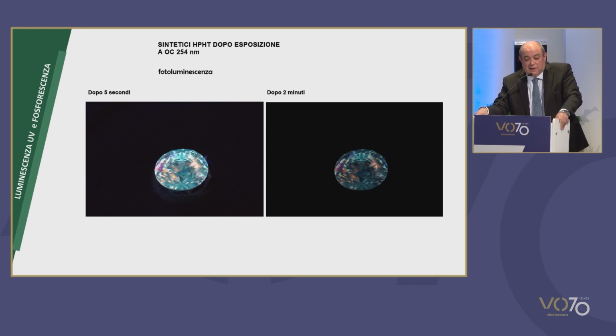Then, speaking about ultraviolet rays, this is another important characteristic. Now, the diamonds produced by high pressure and high temperature, well, most of the stones that we have seen have this characteristic. They remain lightened. Well, it can happen also for natural stones, but this effect will expire in just a few seconds, just 1 or 2 seconds. Well, after 5 seconds, we have this effect, and after 2 minutes, it is still visible. So phosphorescence in diamonds is a very, very bad sign.